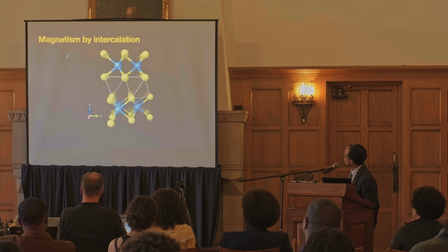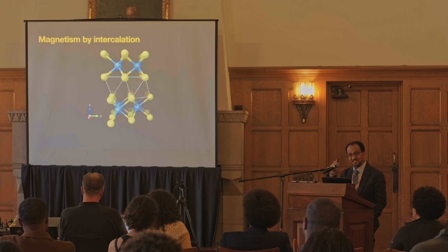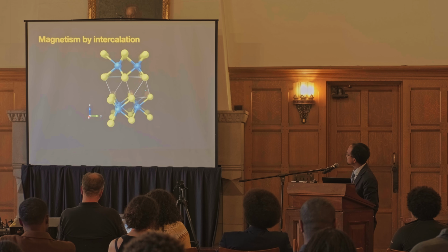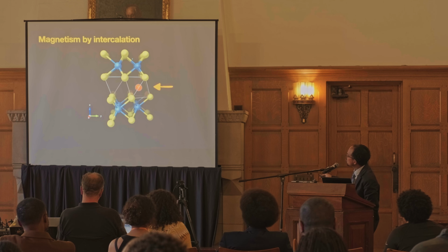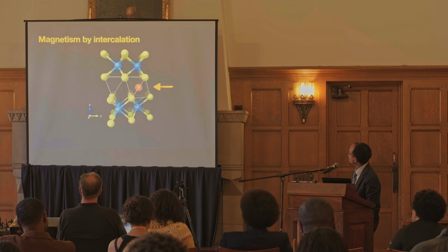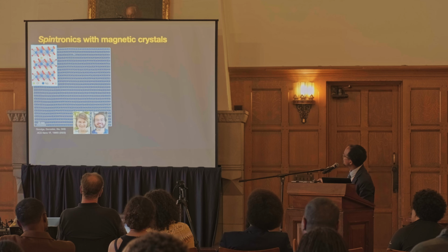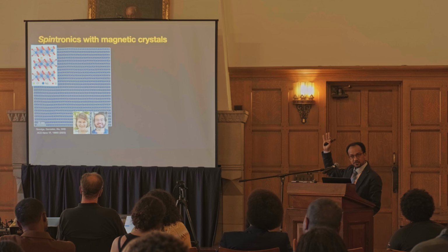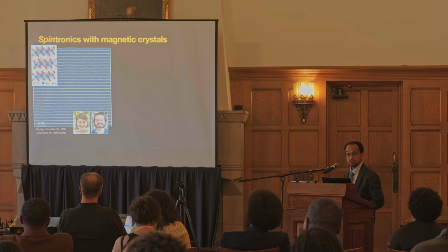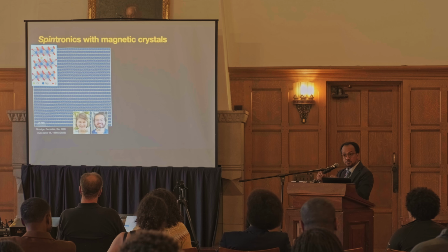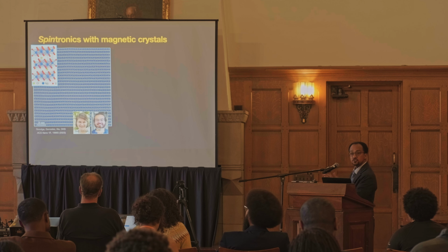Okay, so we take two-dimensional materials, and the way we design some really interesting magnetic crystals is by, I would like to say, trapping atoms. That would be very, very cool. But we're putting them between the layers of some other crystal. So we're taking some atom that has unpaired spins, and we're going to put it between the layers of some other crystal, and that looks something like this. So our crystals look like so, where the more continuous dots are the main crystal originally, and then we put other magnetic ions in between, and by controlling the spacing between these so-called intercalated ions, we can control the magnetism of the system.